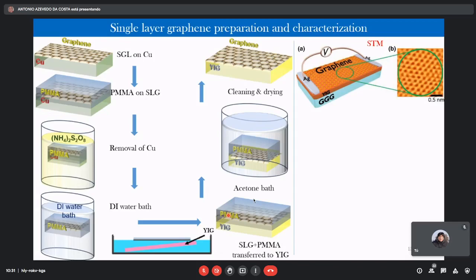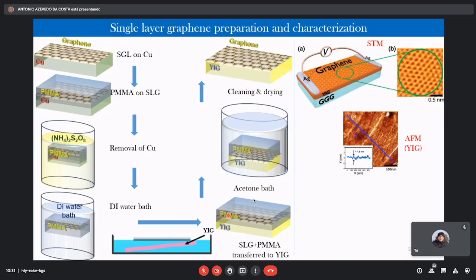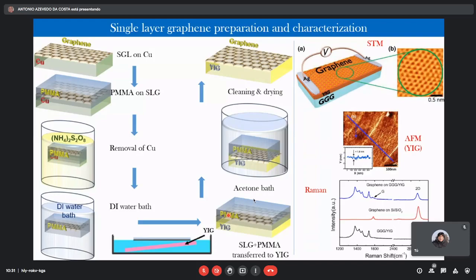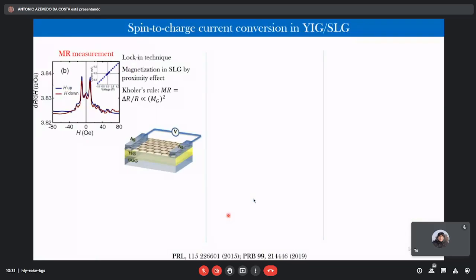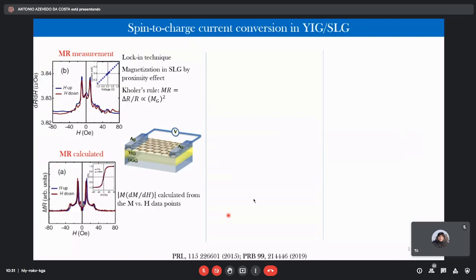So this is an STM image obtained in our system, which is a graphene layer deposited on top of yttrium iron garnet. And for instance, it's a very smooth layer. And for instance, we can make Raman characterization, and the graphene is there. So later we conducted magnetoresistance measurements, and we detected that the graphene, despite not being magnetic, due to the proximity effect, acquires a magnetic property.